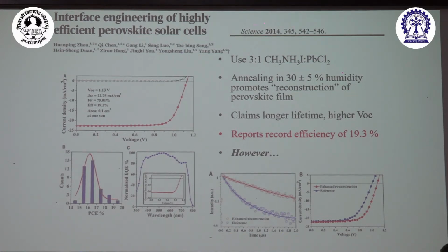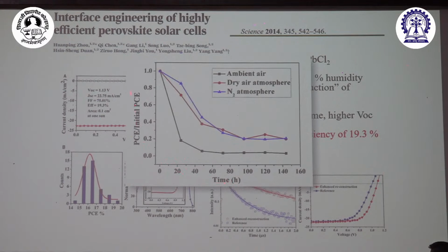And then there was sort of a race to show I can make a higher efficiency cell. And this was a paper by Yang, and it got a lot of criticism because they published in Science, and they claimed a very high efficiency, 19.3%. However, that didn't last long. The stability was maybe 20 seconds or something, right? When you make it first, they show it, then they do it, they got these curves and everything. They reported, again, that's their solar cell distribution of efficiencies. See, the time versus PCE, how quickly the efficiency dropped. So they were not stable at all when they made it. Although they claimed high efficiency, it was not stable. It was just when you turn on the lamp, that's what they show.